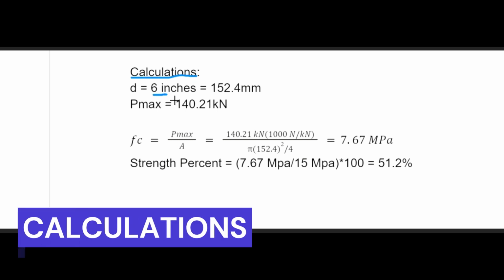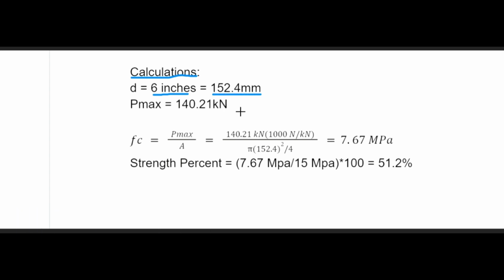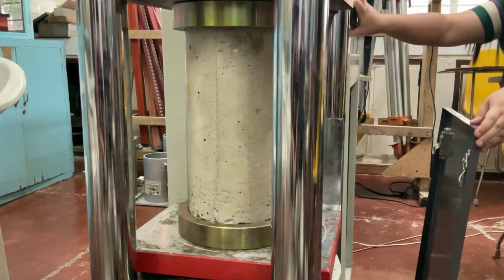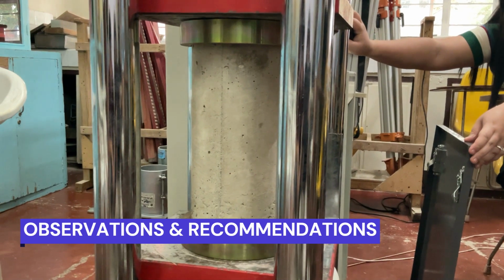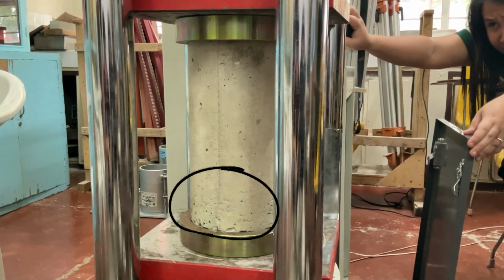Calculations. D, or diameter, is equal to 6 inches or 152.4 millimeters. P max, or maximum load, is equal to 140.21 kilonewtons. Thus, Fc, or the specimen's compressive strength, is equal to the maximum load over the cross-sectional area, which is equal to 7.67 megapascals. Thus, the strength percentage is equal to 7.67 megapascals over the original total strength for Class A, which is 15 megapascals, times 100, equals 51.2%.